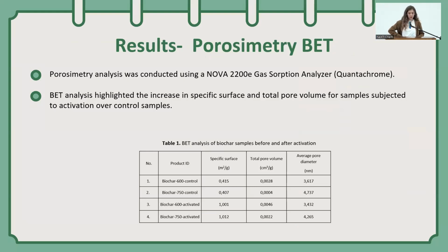And with porosimetry analysis using a gas sorption analyzer, we saw how our activation method had some positive effect on the structure of biochar. More specifically, we saw an increase in specific surface and total pore volume in both our samples. So regardless of the temperature we used at slow pyrolysis, we obtained higher specific surface and total pore volume in both our samples. And if we talk about temperature, we saw some increase in average pore diameter when we use a higher temperature in the pyrolysis.